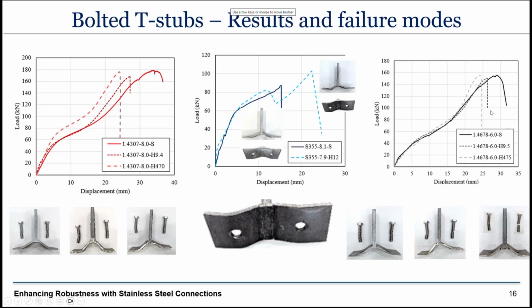For the novel 1.4678 material, we got very similar overall observations. So with increasing strain rate, nothing changes too much in the elastic range, but we get a smaller displacement at failure and a slight drop in the overall strength.